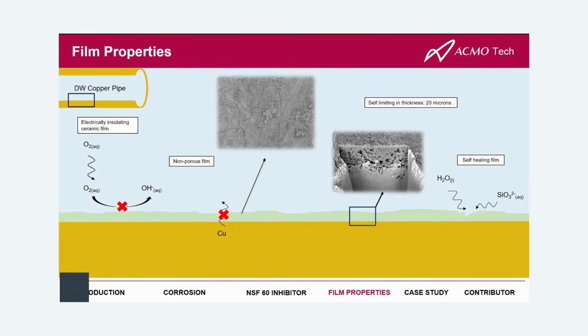Now, second really important point is that the film is non-porous. And this is a real image we took of a film, one of ours that we had in a building. And the film has no defects, right? So that cracking, that's just from the vacuum, from the electron microscope we used. But the film has no defects, so nothing can get to the underlying copper through the film, and the copper cannot escape the film. So you're actually halting the copper from being released, and you're saving the integrity of the